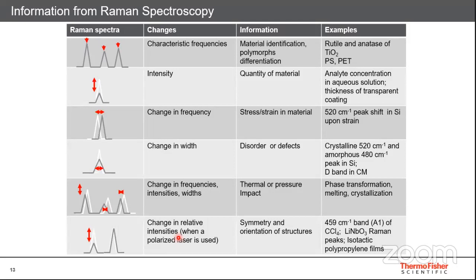Also, if you use polarized light, similar to IR, infrared spectroscopy, you can use it for understanding the symmetry or orientation of your structure. For example, if a particular group in the molecule is oriented at different angles, then with polarized light you can see that the intensity of that particular peak will vary depending on the orientation of that group. For example, in a polymeric structure, you can correlate that using Raman spectroscopy.